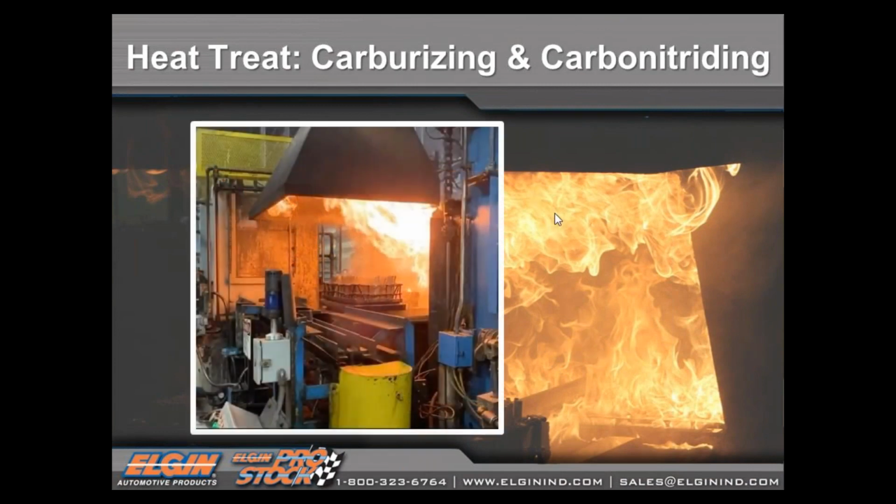One of the other processes that we do, which is a kind of a combination process, is called carbonitriding. Most of you have heard of nitriding, which is put on valve stems and such to give you advanced wear properties. Valves are already made out of very good materials that are heat treated and/or stainless. The nitriding that's on a valve is a very, very thin, very long process to apply, and it's less than 1/1000th thick. So in the valve train parts, other than the valve stem, like your rockers and push rod ends, your pivots, those are all going to either be carburized or carbon nitrided.